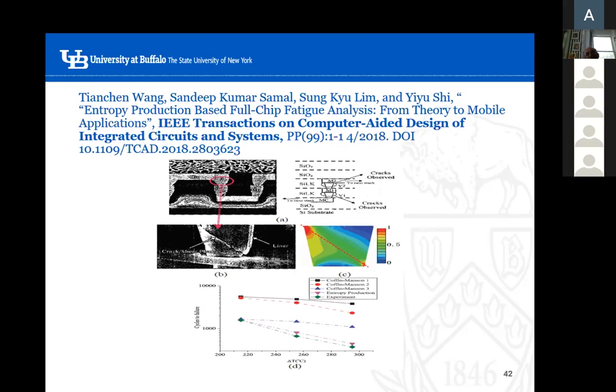Because Coffin-Manson is obtained from a sample, not from the computer chip, and then used. Essentially, when you do the experiment to get the parameters for Coffin-Manson, you don't test the chip, you test just the material that you are using it for, like the solder. And then you obtain the parameters, and then you use it for prediction. But here, as you see, they cannot predict.